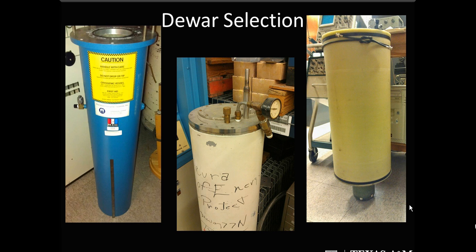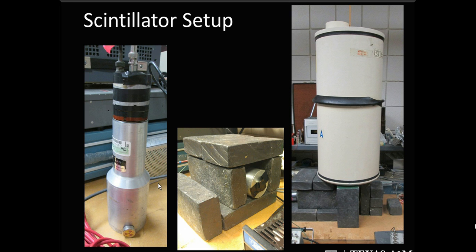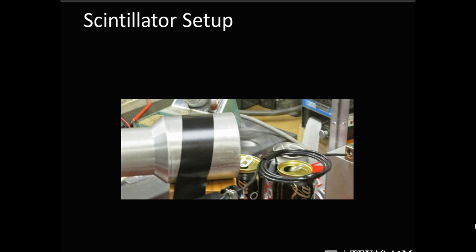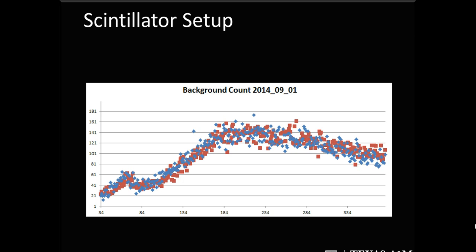And we can get the scintillator right up against the sample and get a nice big solid X-ray field onto the scintillator. It's a 3-inch sodium iodide crystal, magnetically shielded with a photomultiplier tube. We shielded it with lead bricks, and we tested it with sources in the Dewar. And it is linear between 22 keV and about 500 keV of X-ray energy, so it fits the bill for what we need. We have also tested it near the pulsed magnetic field that we're going to use, and found that the background caused by the pulsed magnetic field was negligible.